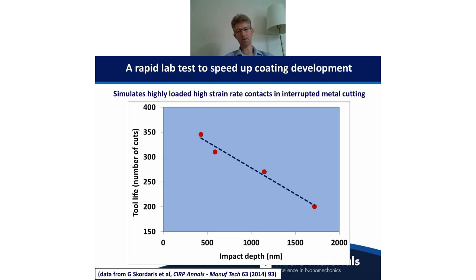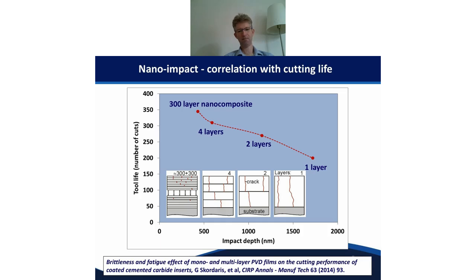So if we now look and say, well, what is behind this trend? What we can see here is how our customers manage to optimize their coatings. In this case, is by tinkering with the microstructure. So they're putting extra layers in, and these extra layers are acting as stopping through thickness crack propagation. So the cracks are coming in, but then they're getting deflected perpendicular to the stresses, and this is minimizing the amount of wear that's occurring essentially. So it's localizing the fracture, and it's minimizing the amount of through thickness cracking.